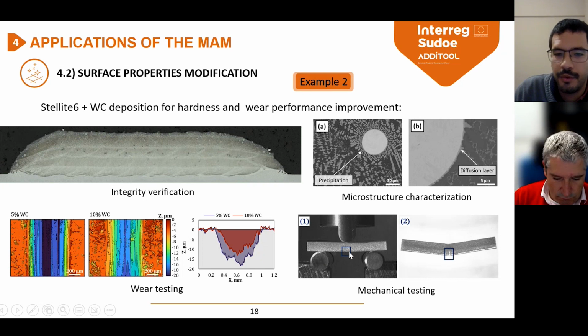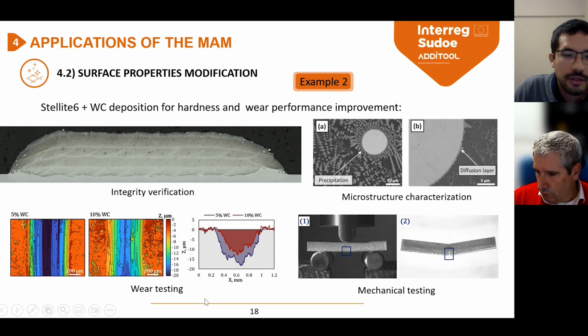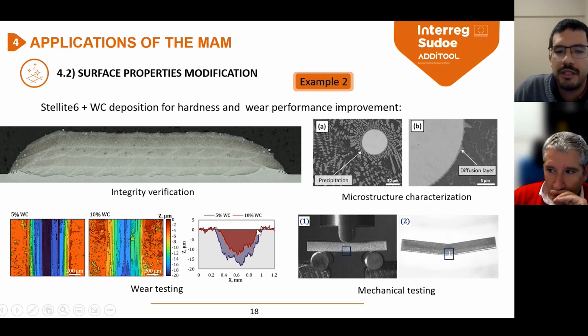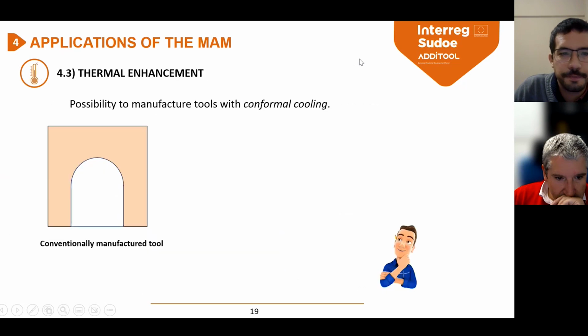Once we have ensured the integrity of the clad, we have analyzed the performance, both mechanically through the three-point bending test, and also the wear performance of this clad. And as you can see in this figure, increasing the tungsten carbide percentage implies higher resistance to wear problems, which is really interesting, for example, in the tool and die industry.